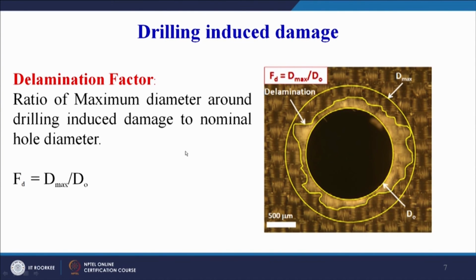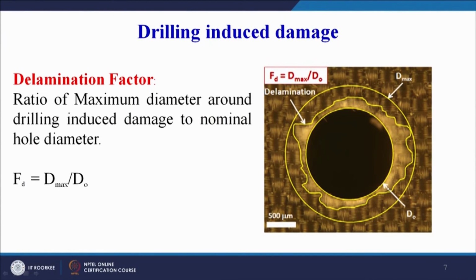Nominal hole diameter is our target diameter. So we usually quantify the damage around the drilled hole by the delamination factor, which is very simple. FD is equal to Dmax by D0. Here you can see in the diagram, this is the damage, the light color portion is the damage, and in this damage you can see the maximum diameter of this damaged area, Dmax, is in the numerator, and our original diameter of the hole that we wanted is in the denominator. So this is Dmax by D0, which gives us the delamination factor.